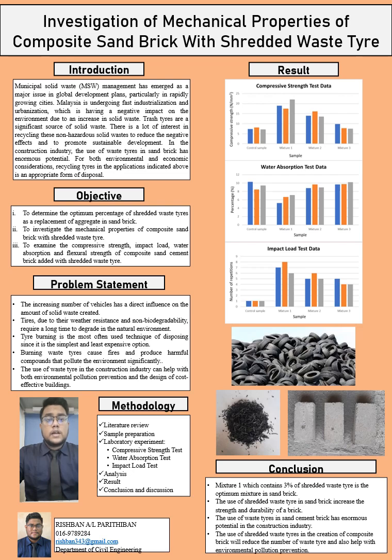Now, let's see the results. Graph 1 shows the compressive strength test data. From the result of this test, it can be concluded that mixture 1 has the highest compressive strength, which has an average value of 19.53. Control sample was recorded as the lowest compressive strength, which has an average value of 7.53. The result implied that bricks with more percentage of shredded waste tire generally cannot withstand load, and the increase of shredded waste tire gradually decreases the compressive strength of a composite brick.